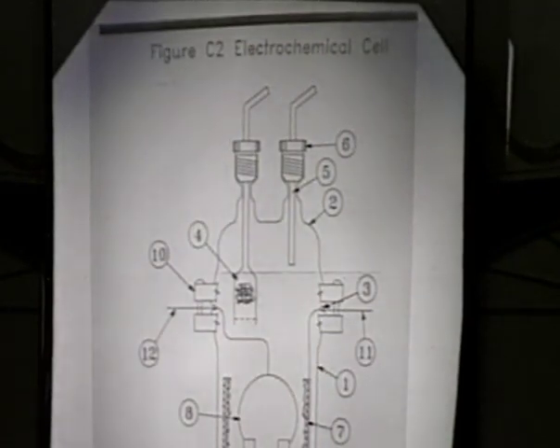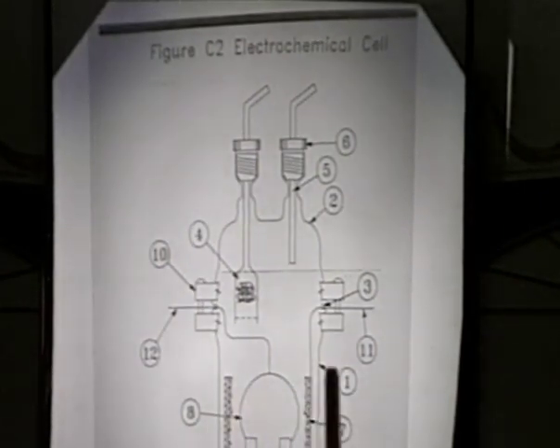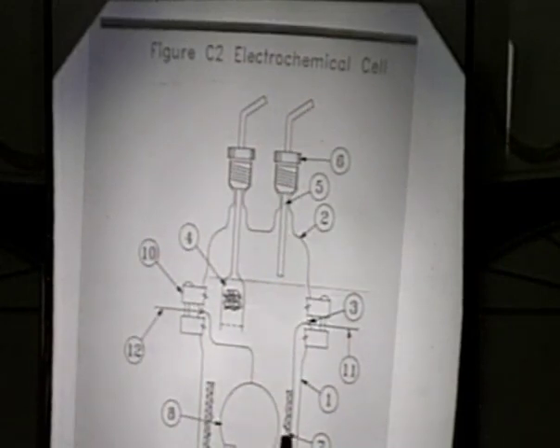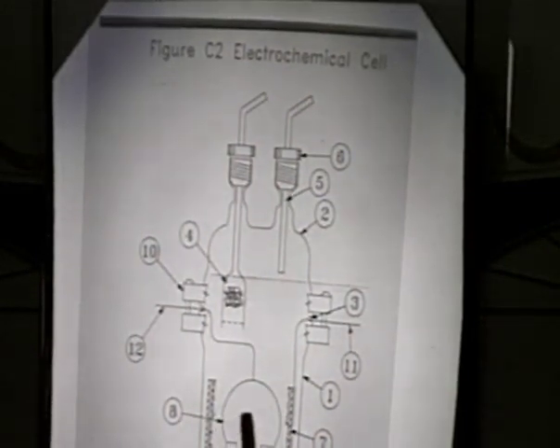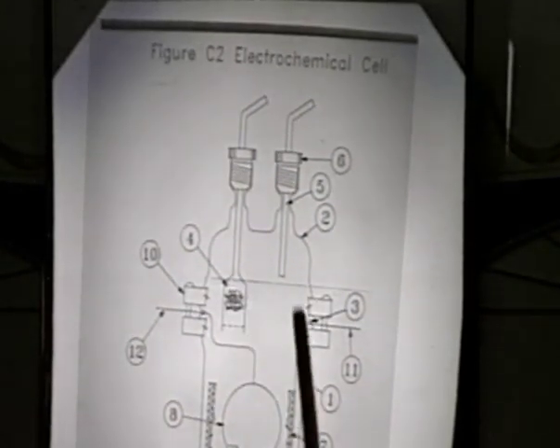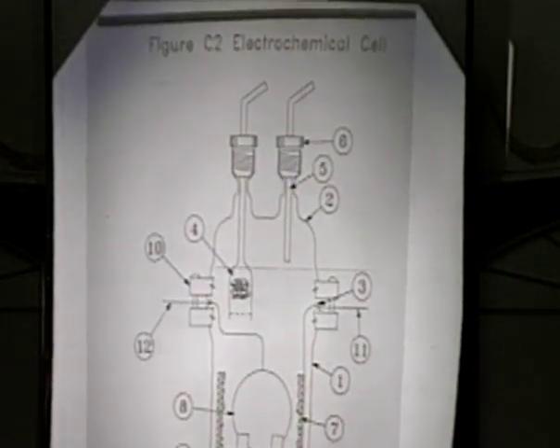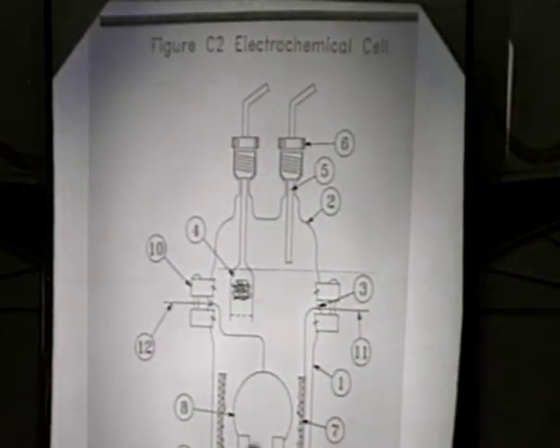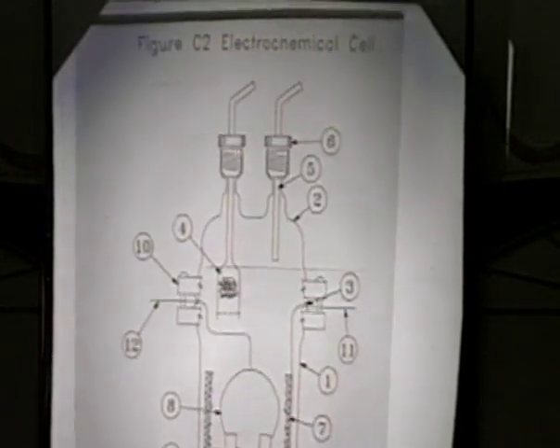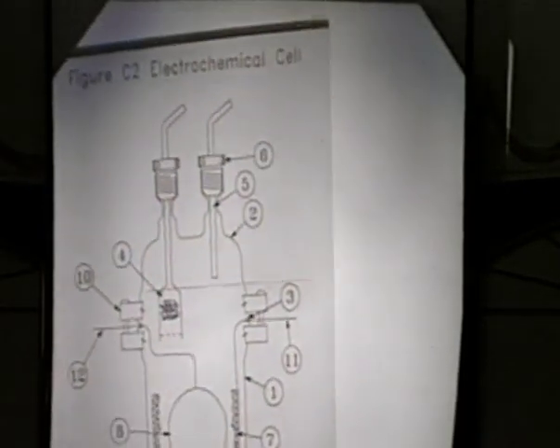The cell itself was slightly redesigned. Instead of using the plating of the platinum, we had the platinum mesh. And now we used a different piece of palladium. This was an ingot of palladium, a rod, essentially, from which we cut something like a thick quarter, machined the edges, except the cast rough edge over there was left as cast. And here's the recombining electrode over here. This vents the excess oxygen to a bubbler, to a mass spectrometer, which allows us to figure out how much deuterium is going into the palladium there. This is just the electrolytic cell by itself.